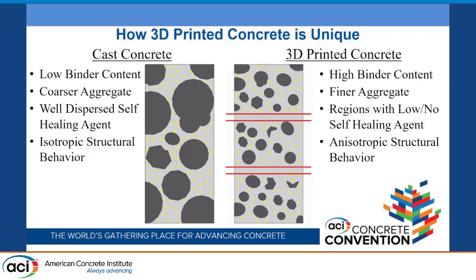All this means is that you're going to have a larger magnitude of shrinkage, which is going to amplify all of your cracking issues. Secondarily, we have our interlayer areas in our 3D printed concrete. Those interlayer areas are typically much more significantly paste rich, meaning that we have potential for a region of lower self-healing agent concentration. This is something that we're trying to prove. Additionally, in these interlayer areas, there's generally a higher air content.